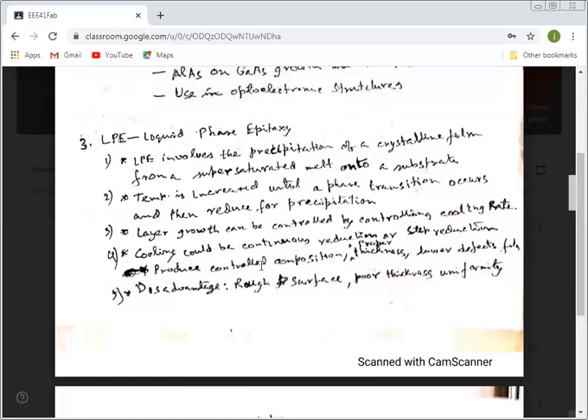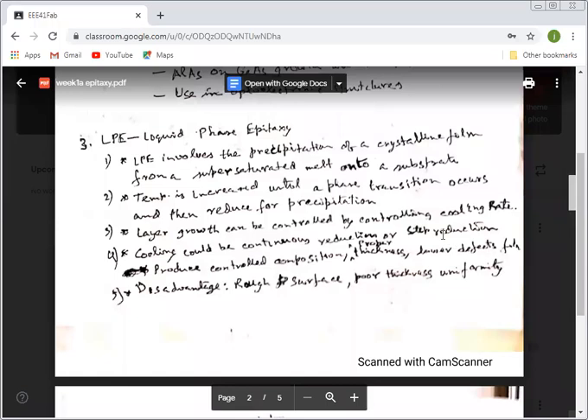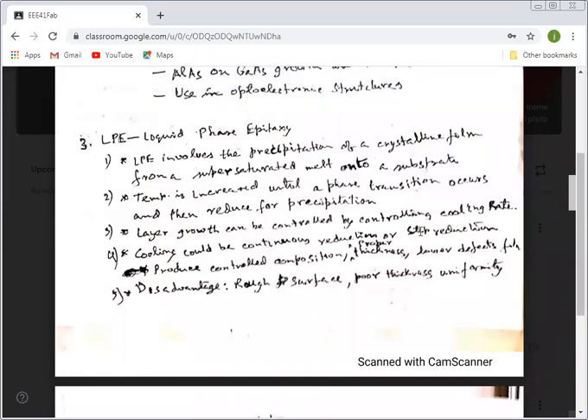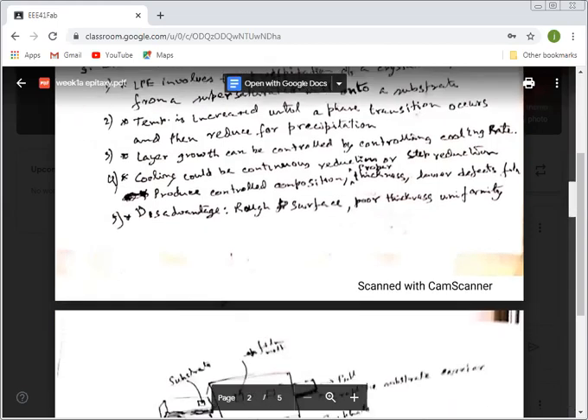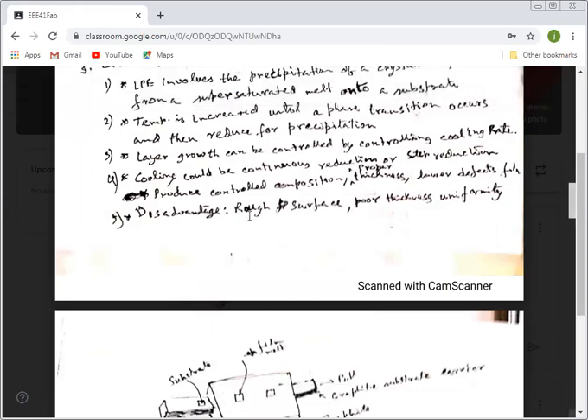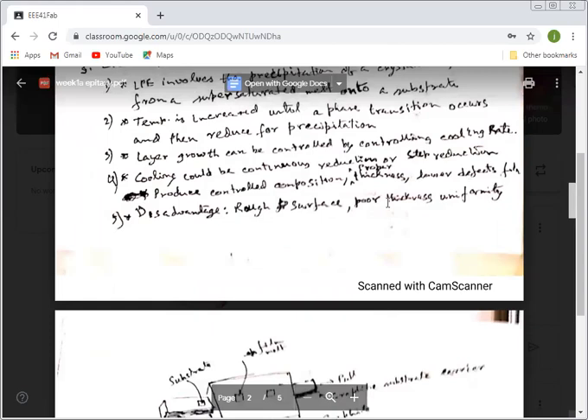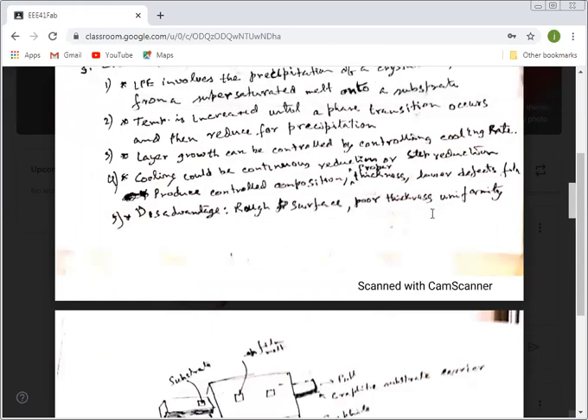If you want a more controlled composition, proper thickness and lower defect film, then we use a step reduction. In the step reduction, we reduce the temperature for some time and then we stop it, again we reduce it for some time and then we stop it. This way we do the step reduction. When the reduction is done, it will crystallize layer by layer, and we will have a smoother and lower defect film. The disadvantage of liquid phase epitaxy is that the surface is more rough. It is not smooth, and has poor thickness uniformity. So the thickness is not uniform.